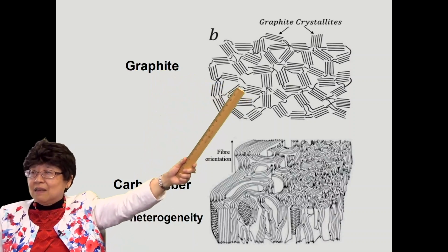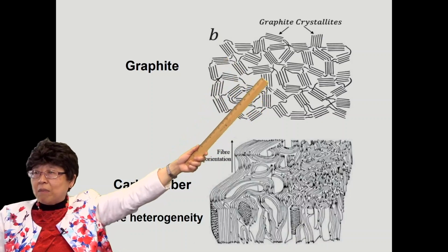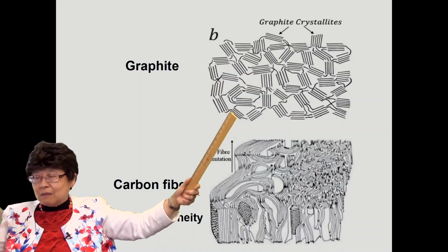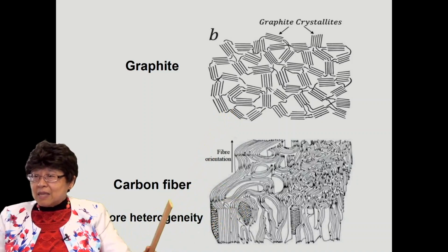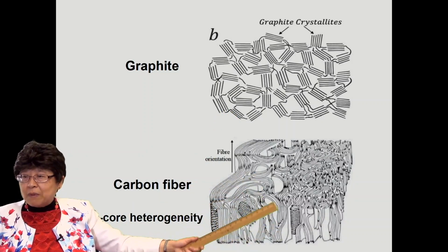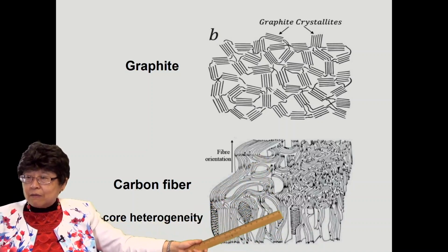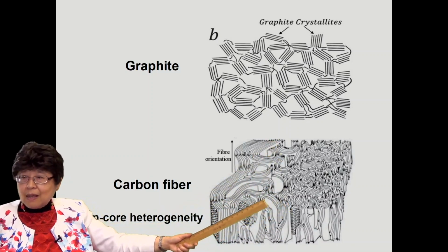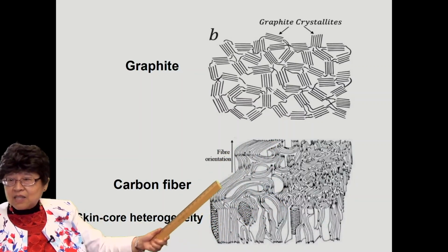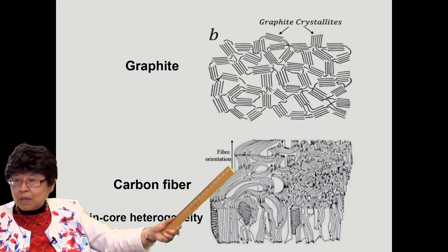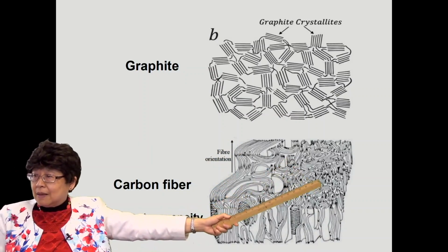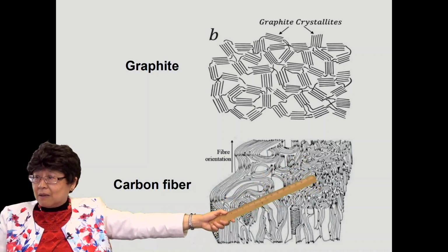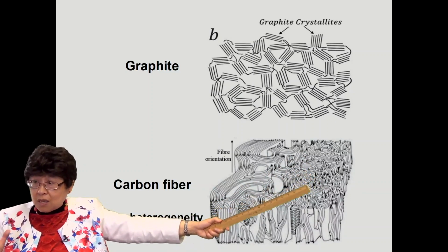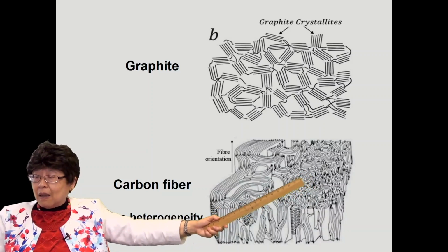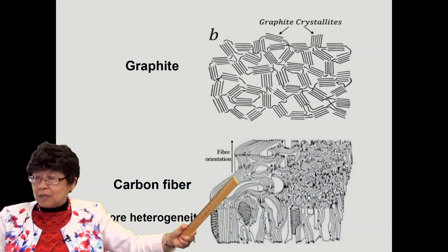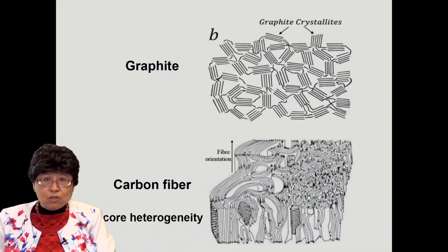This is synthetic graphite. In synthetic graphite, you have these graphite crystallites kind of randomly oriented. But in the case of carbon fiber, you can see that the carbon layers preferentially are along the vertical direction, that is the fiber axis. However, the skin has the carbon layers more parallel to one another than in the inner part called the core. See, the carbon layers are more crooked, though still preferentially oriented vertically. So we call it a skin core heterogeneity.